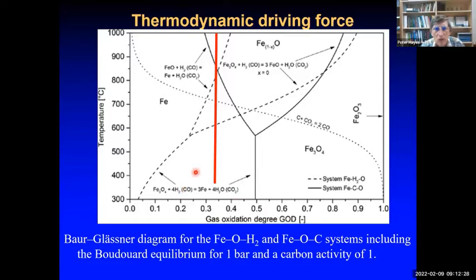So if we're thinking about the driving force for a reaction, we find that for a given composition here, we have no driving force in the case of hydrogen-steam until we get to at least 850 degrees centigrade. On the other hand, if we're talking about the CO-CO2 system, we find that the driving force is actually reducing. That is, the difference between the red line and the phase boundary is decreasing as we go up, and in fact becomes zero at 850 degrees centigrade. And if we want the reaction to proceed, we actually have to add more CO, so depart from this reaction. So you see that just increasing the temperature affects that driving force, which is a critical part of it.